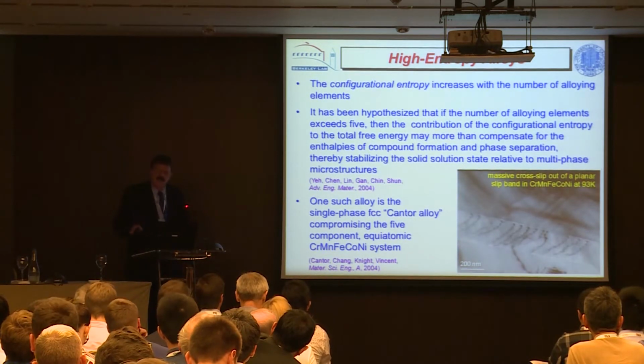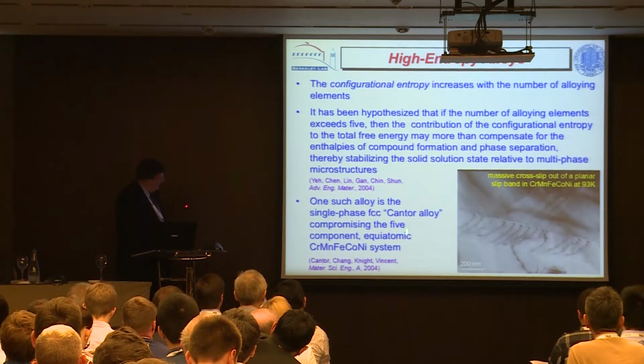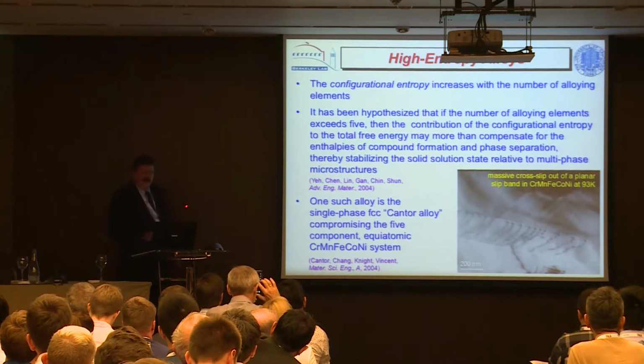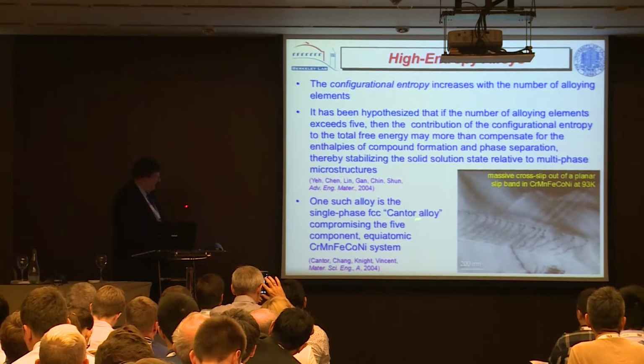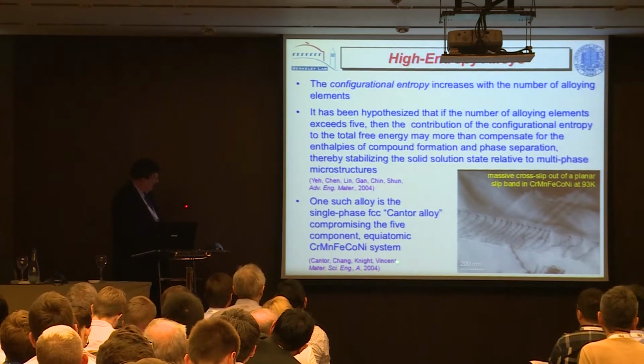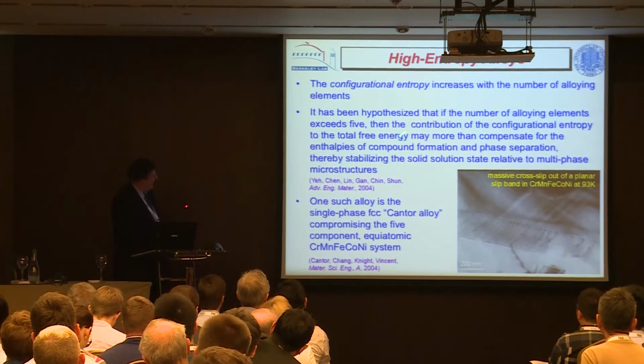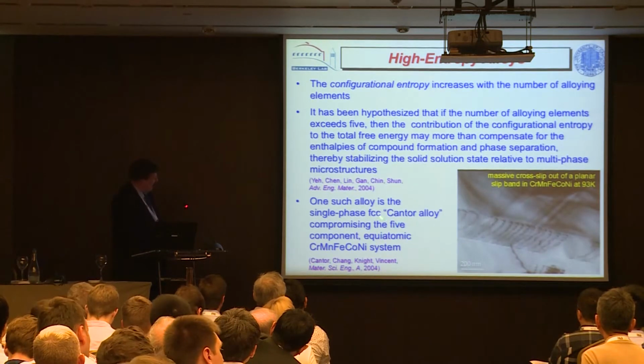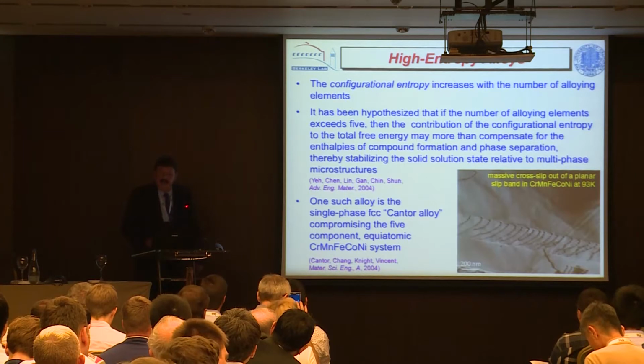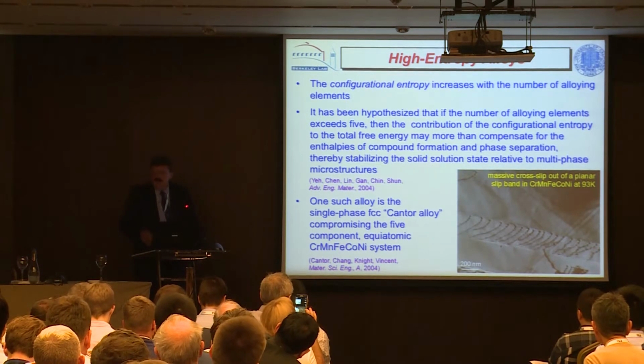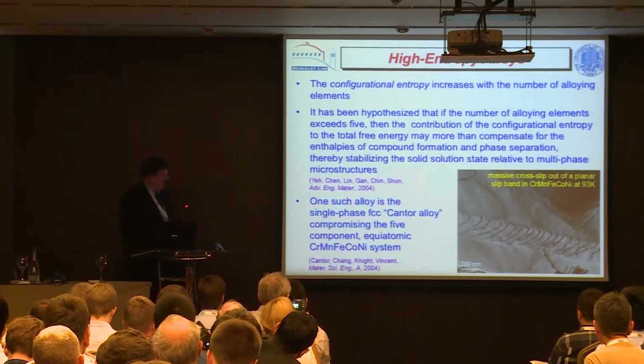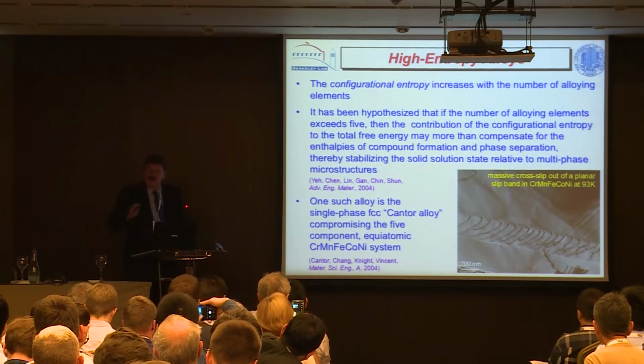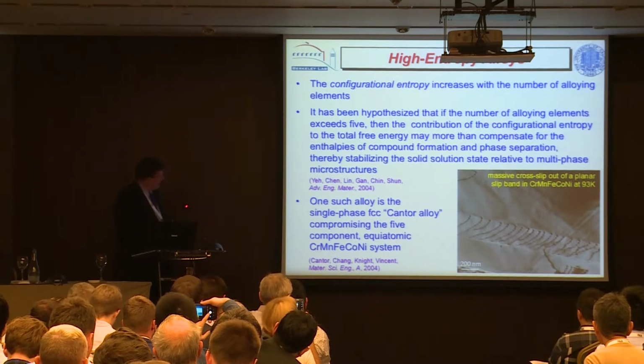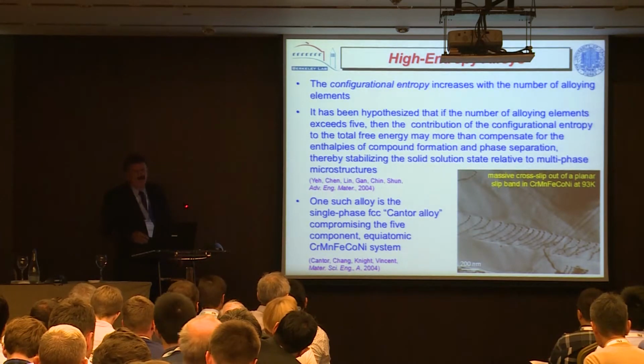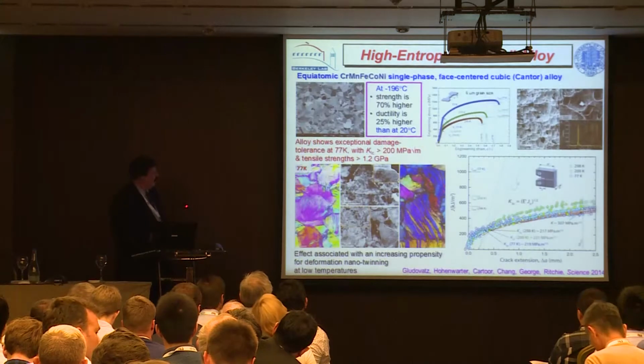Now, we don't think that's true anymore, but the alloy that's closest to this was done by Ye initially in Taiwan, but my buddy Brian Cantor in England also was trying to do this. He didn't coin the term high entropy, but he came up with what is now being known as the Cantor alloy. This is a chromium manganese iron cobalt nickel system. Variety of crystal structures there, but it forms a single phase FCC material. This is probably the most popular high entropy alloy.